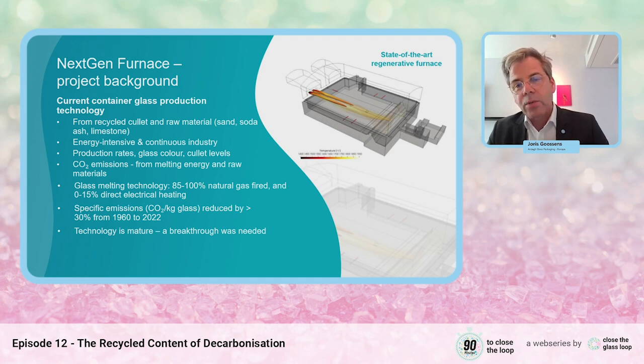So in the current technology, we use furnaces you see in the upper right corner, the state-of-the-art gas-fired regenerative furnace. And these furnaces are used to convert the raw materials, where cullet is the main raw material for container glass production, cullet and raw materials like sand, soda ash, and limestone, into a liquid. So they have to be dissolved at high temperatures into a liquid, so that the liquid glass can go to the forming station to be formed into bottles. And because it requires a high temperature, it's an energy intensive industry, and we run these furnaces in a continuous way. And typically these furnaces run up to 15 years.